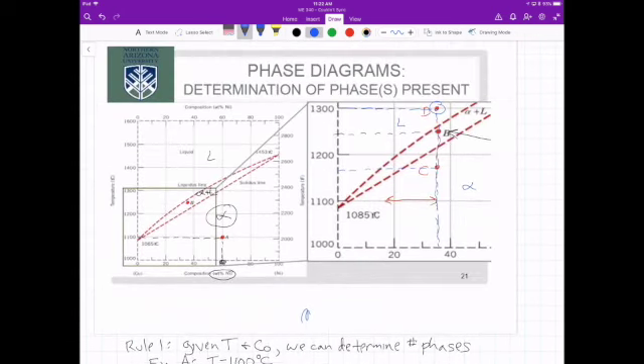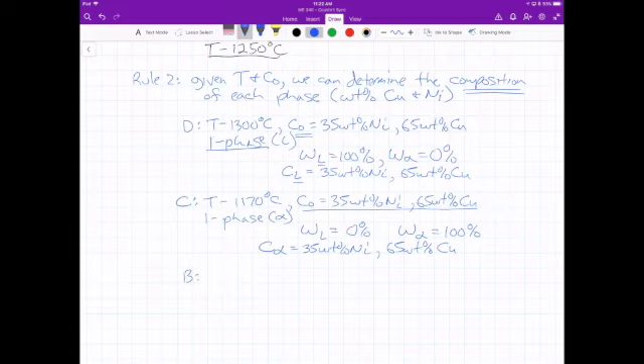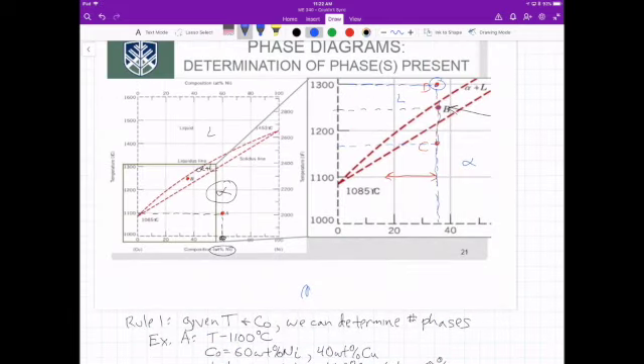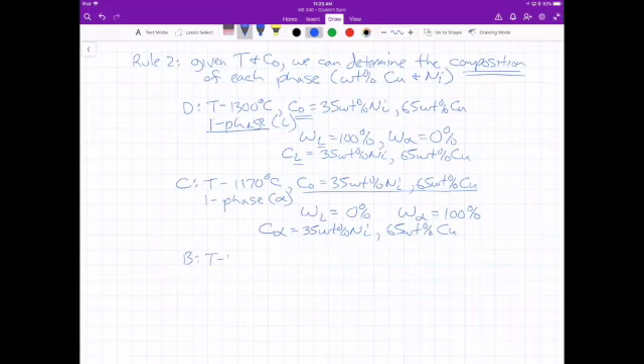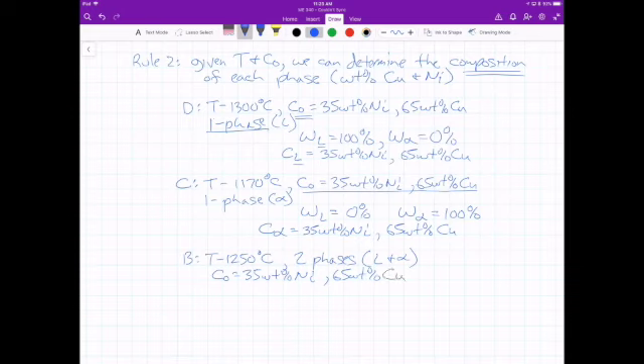What's going on at point B? We are in the dual phase region. We have liquid and solid that exists in this region. So let me write that down first. The temperature looks like about 1250 degrees C. We have two phases, liquid and solid. Our initial concentration, like I said, is always the same. We bought this material at 35 weight percent nickel, 65 weight percent copper, and we're just changing the temperature. But how much of each of these materials exists in each of these phases? That's what we need to calculate.